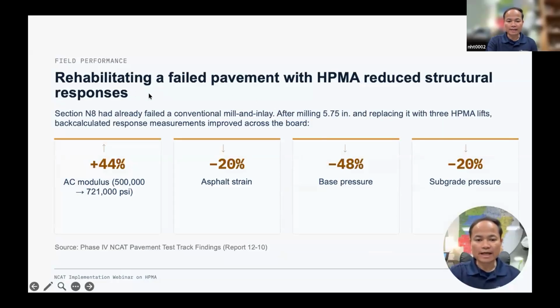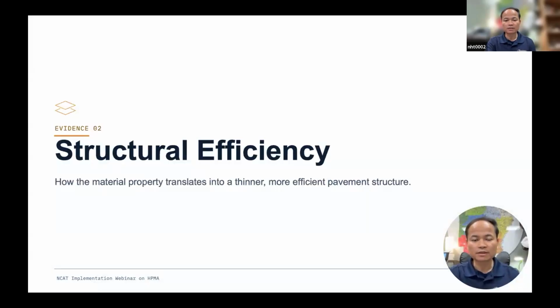Now, for the N8 section, after we rehabbed that section with the HPMA, you can see here Dr. Tim did all the testing and conducted structural analysis with the strain gauges and base pressure plates in the whole structure. You can see here the AC modulus, when you do the back calculation, increased by 40, 44, 45%, significantly increased. The asphalt strain at the bottom of the failed structure reduced by 20%, and the pressure plates at the top of the base and the top of the subgrade reduced by 48 and 20%. So significant improvement in section N8.